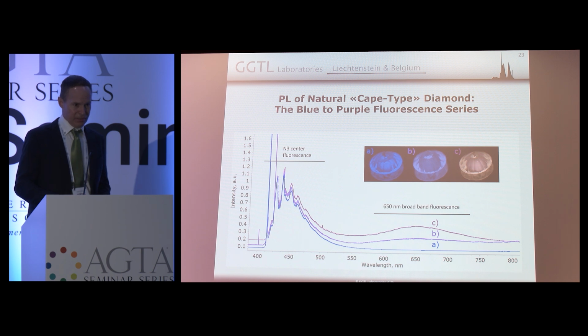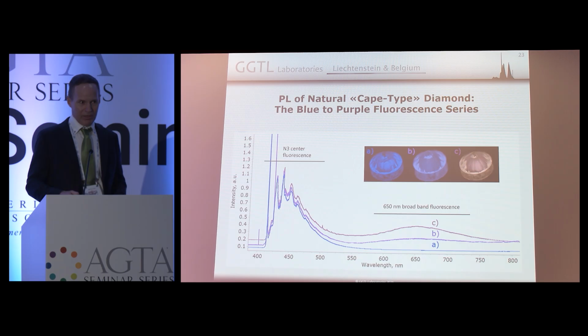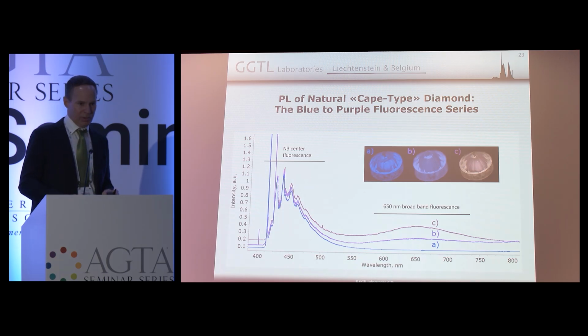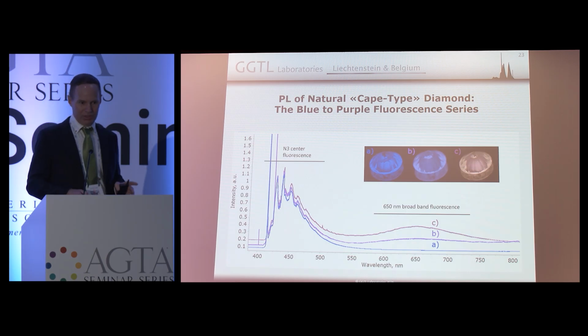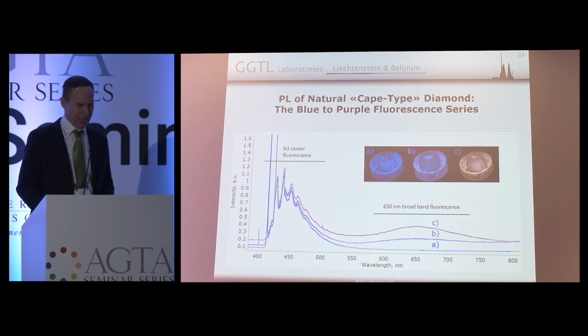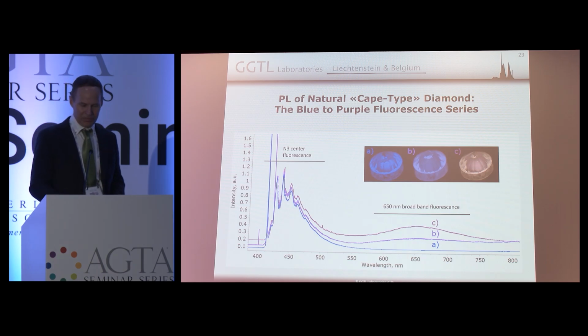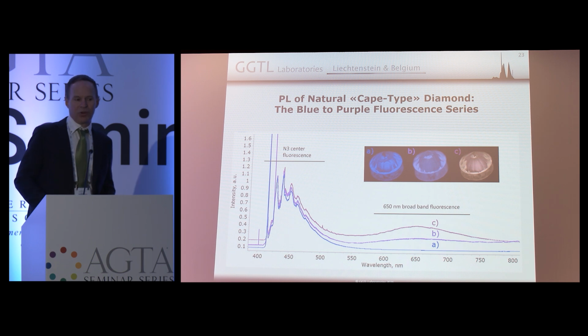There are some synthetics that do contain some of this center, but it's generally weak, or when it's stronger, it's only localized in certain sectors. I'm talking about colorless diamond here. If we talk about yellow diamonds, this criterion does not hold, because they treat them, they create N3 centers. You can have strong N3 centers in synthetic yellow diamond, but not in colorless. In colorless, it has been described. Generally, what I have seen, they're localized only in lamellae within your stone, never throughout the stone. And I still haven't seen a stone that fluoresces strong.